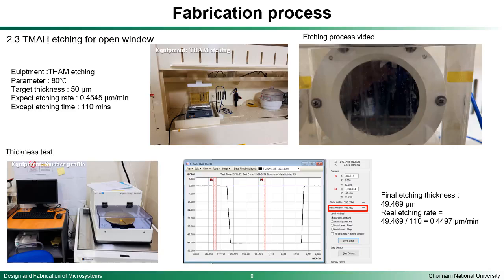And the expected etching rate is around 0.454 micron per minute. So based on the target thickness and the expected etching rate, we have calculated the expected etching time is around 110 minutes. So we just put our sample into the TMAH equipment to do the etching.